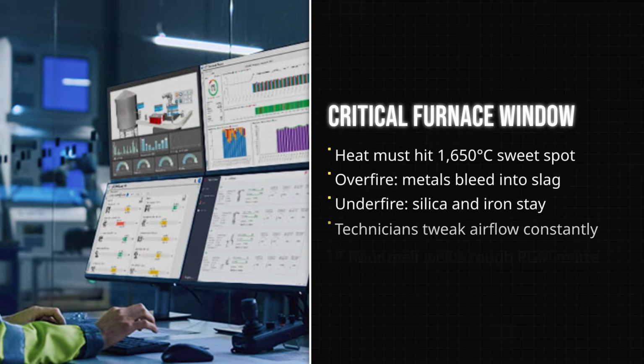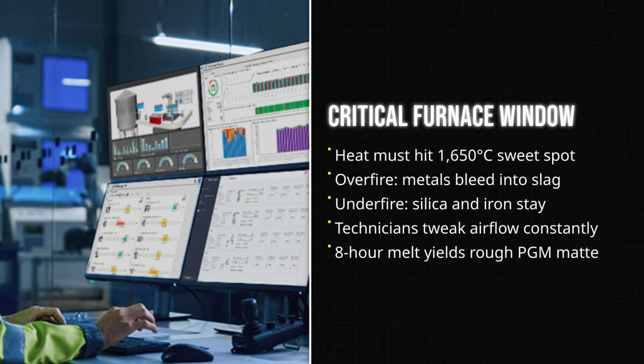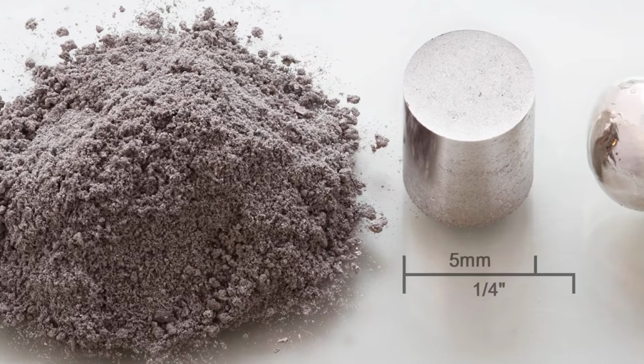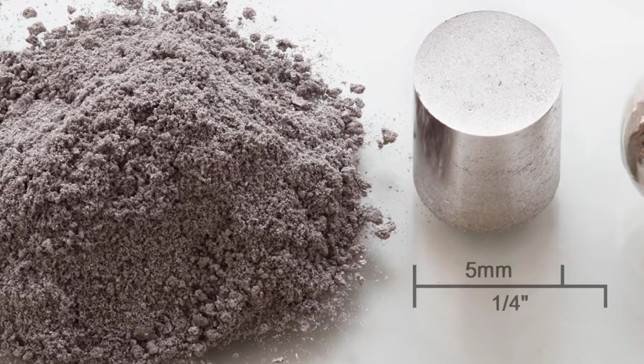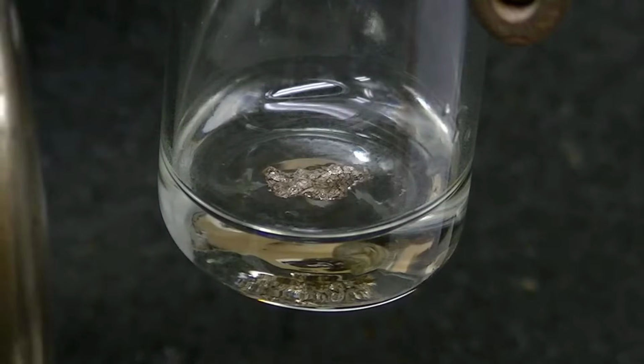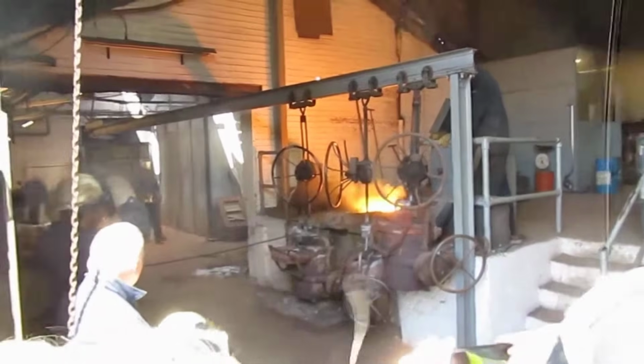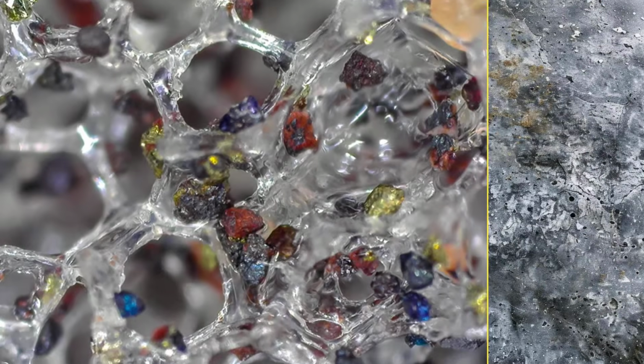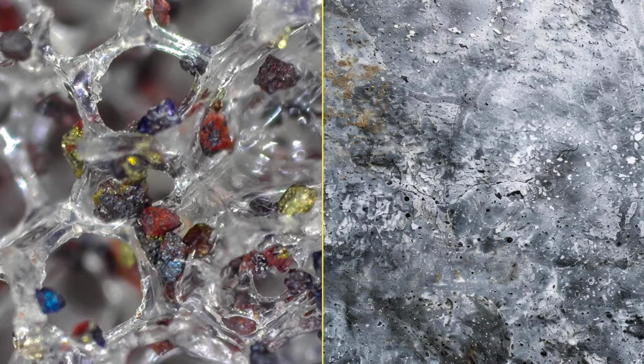Timing is critical. Too long, and precious metals are lost to the slag. Too short, and impurities remain. The result is a refined matte, rich in platinum group metals, ready for the next stage, chemical dissolution. In this crucible of fire and control, the journey from rock to rare metal crosses its first threshold.